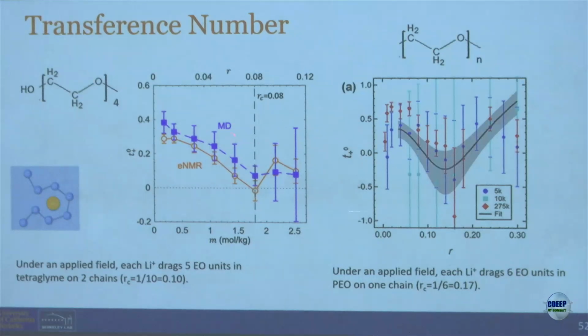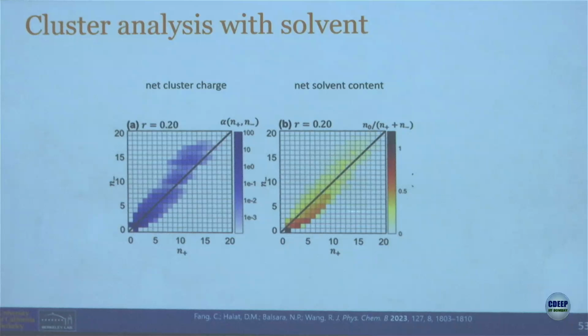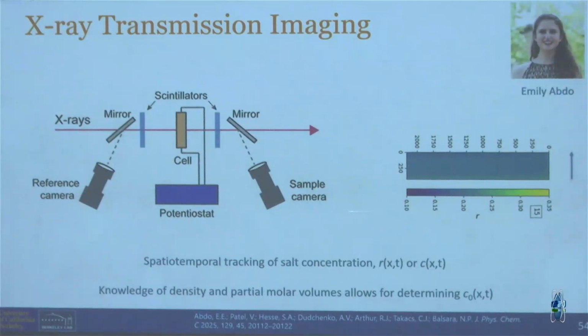So you can, in fact, even rationalize the difference between this minimum being at one value of R, 0.16, and this at 0.08 because of that effect. And so under an electric field, this ion is dragging 5 or 6 EO segments. And in fact, when you do the same analysis that was described by the MIT group, what you find is that the MIT group defined the cluster, but they didn't worry about how many solvent molecules were in each cluster. And if you take that into account, that dominates transference in our case. Okay. So, and that is the bottom line.